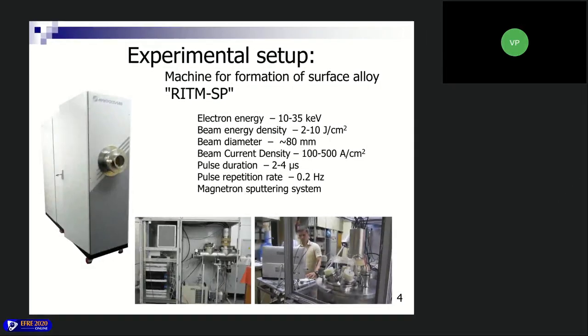So the experiments were conducted on an experimental setup, the machine RITM-SP, which is based on a source of low energy, high current electron beams, which was developed at the High Current Electronics Institute in Tomsk. This machine has an electron energy in the range of 10 to 35 kiloelectronvolts, and the energy density of the beam can be varied from 2 to 10 joules per square centimeter.